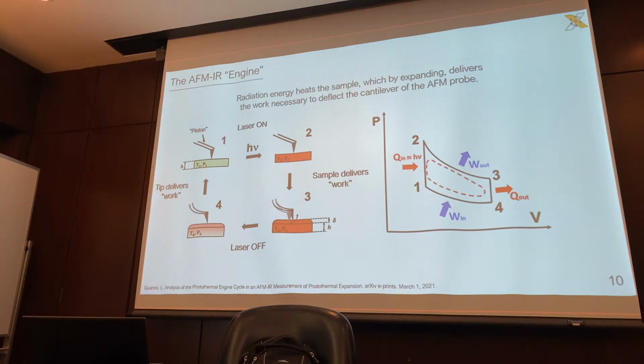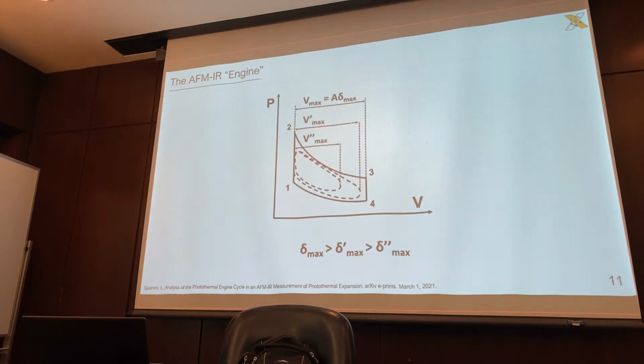From position 1 to 2, max pressure is at the peak temperature here. Max volume is reached in position 3. At this point, we begin to lose our heat, and so we see this rapid loss of volume, or loss of expansion. And then in this case, the tip actually delivers work to the sample. We're going to go over 2 different processes in which they model this.